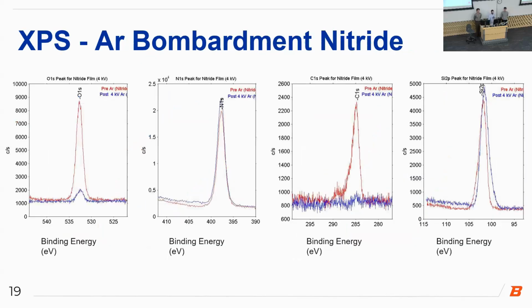Okay, so now let's take a look at the XPS result for the nitride after argon bombardment at 4 kilovolts. Red is before treatment, blue is after treatment. So as we see, the oxygen peak dropped significantly after bombardment, meaning the native oxide sitting on top of the nitride was removed. The nitrogen peak stayed, confirming the nitride film is still there, and the silicon peak increased slightly. So together, these changes tell us that argon exposed the true nitride surface underneath.